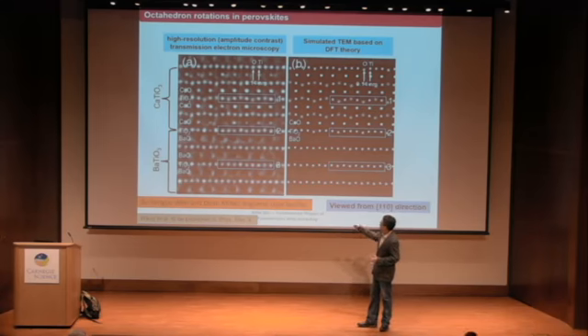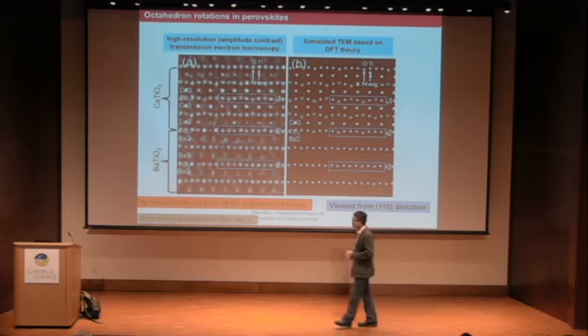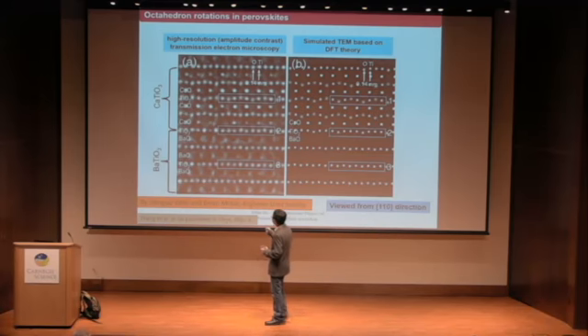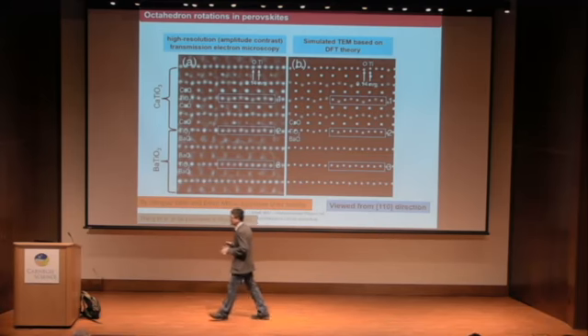In the bulk region, calcium titanate, you see a large tilt. This is the alteration tilt due to the antiferrodistortive rotations. If the TiO2 layer is sandwiched by one CaO and one BaO, you see the tilt is still there, but largely suppressed.